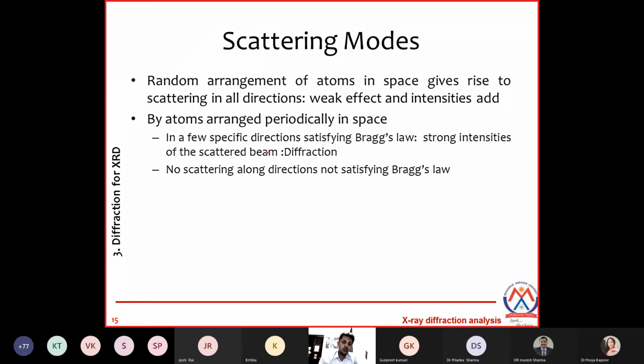One more thing: you are getting a very high signal in a few directions, but the maximum intensity of the XRD is at the transmission. So the detectors are not put in the transmission line because that signal is very high. The detector is always kept at some angle. So we never measure the transmission signal from XRD equipment. There are a few requirements that need to be fulfilled to get the XRD signal.